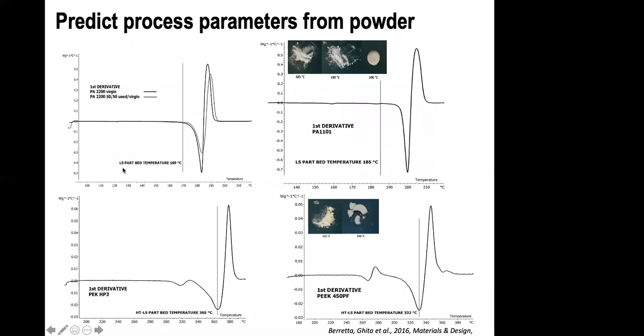I'll come back here just to explain that in the images we have on the right, we tried to understand a bit better. We know that if the bed temperature is within the melting peak for the polyaryl ether ketones, at the end the powder is still a cake, but is still usable. For nylon, we know that if we operate within the peak, we would consolidate the powder. So at the end of a DSC experiment, we opened the pan and looked at the powder to see whether that's still the case. In the case of nylon, as you can see in the image, we were able to break down the powder at 185, at 180, but at 200, which would be the minimum point of the first derivative, the powder was solid. There was a block, impossible to actually break down.